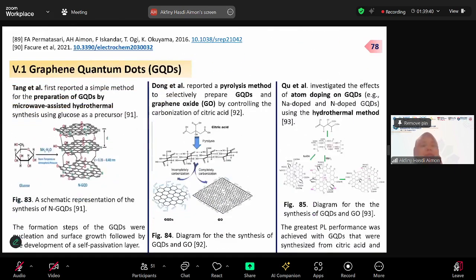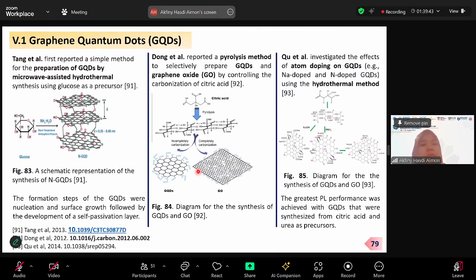Okay, and then Tang et al. first reported a simple method for preparation of graphene quantum dots by microwave-assisted hydrothermal synthesis. After they do hydrothermal, they do the microwave method to reduce the oxygen and to create the dots. The formation steps of the graphene dots were nucleation and surface growth, followed by development of a self-passivation layer.